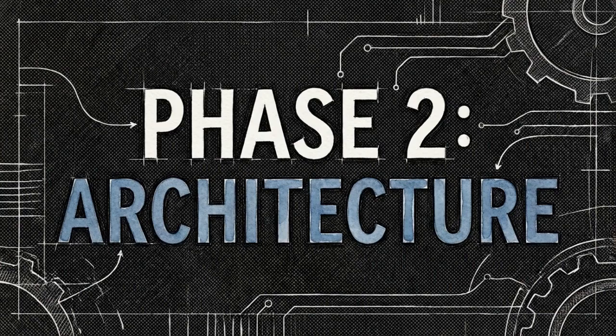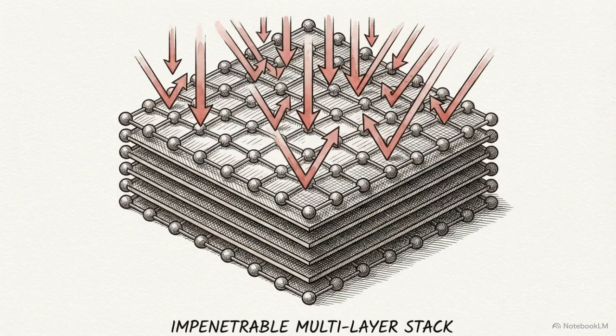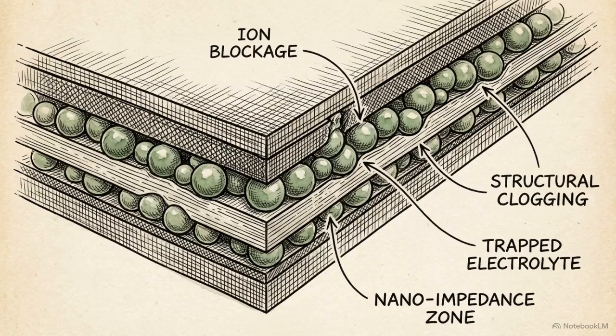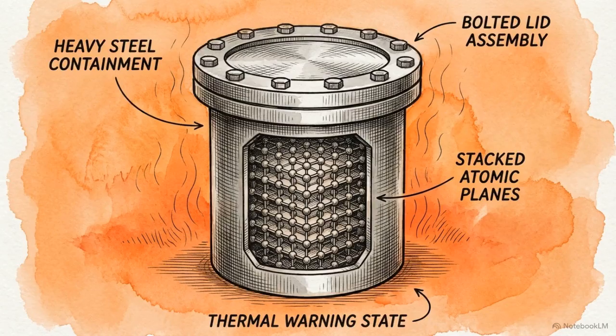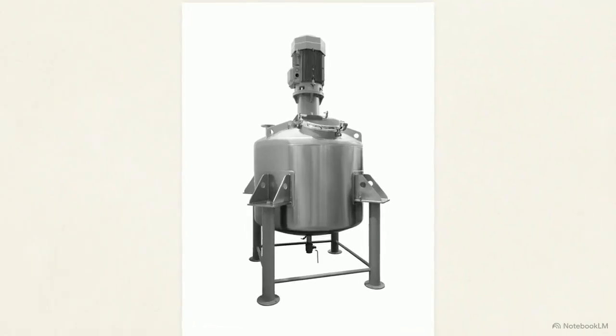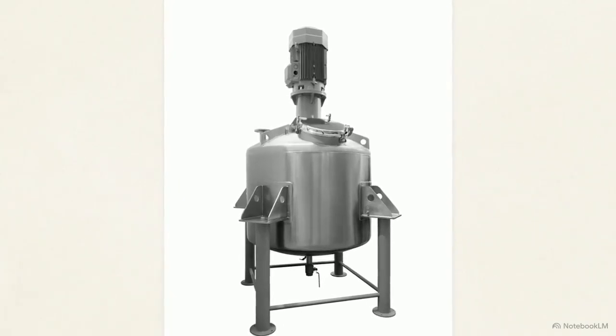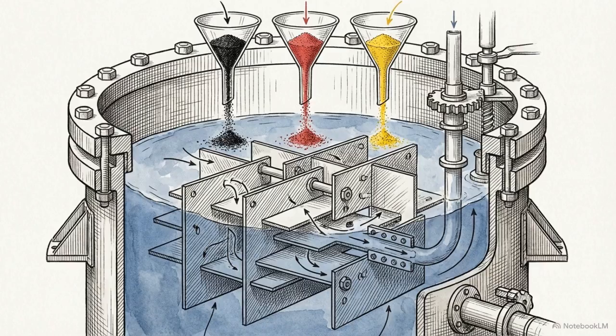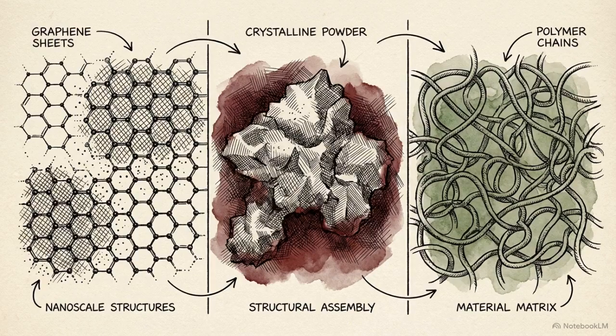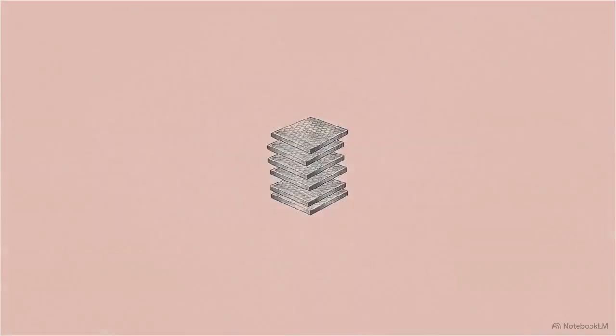With the base material selected, we move to Step 2, structural synthesis. Simply stacking flat sheets of WSe₂ on top of each other physically restricts the flow of ions, severely limiting overall battery capacity. We have to change the macrostructure. We do this using a hydrothermal method, placing the WSe₂ into a liquid solution and subjecting it to extreme heat and high pressure. Inside this reactor, we introduce specific chemical additives: graphene to improve conductivity, iron oxide, and a conductive polymer called polyaniline. The extreme pressure forces these flat layers to peel apart, warp, and lock together with the additives.